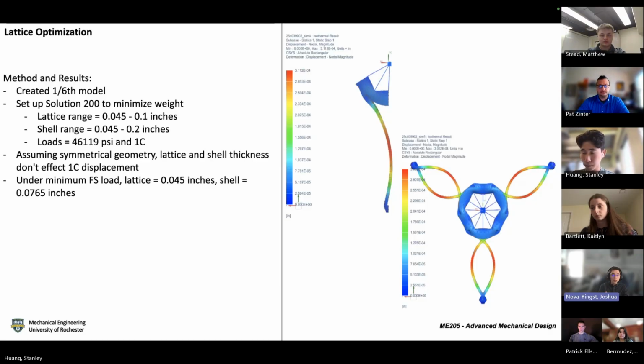With the lattice optimization, we basically found that the lattice has no effect on displacement as long as the part is fully symmetrical. We had displacements on the order of 10 to the negative 12 inches, which is effectively 0. So we ran those pretty quickly and moved on from that.